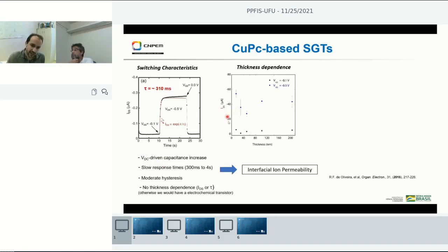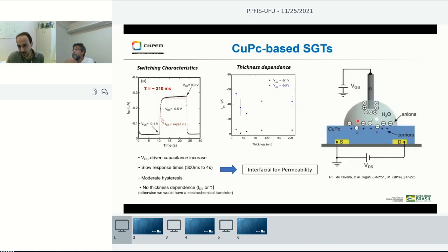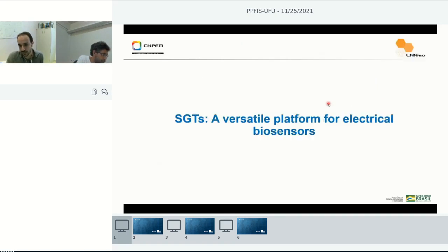However, if we fabricate films with different thicknesses, we observe there is no huge variation of current by increasing the film thickness. So it means that we do not have a complete electrochemical operation, but rather a mild interfacial doping. So perhaps this is a hypothesis that we published. We have ion penetration just in the few layers of our film.